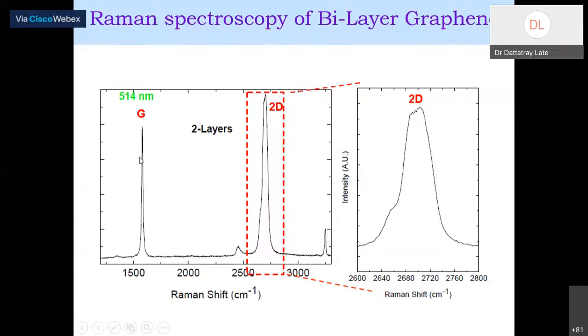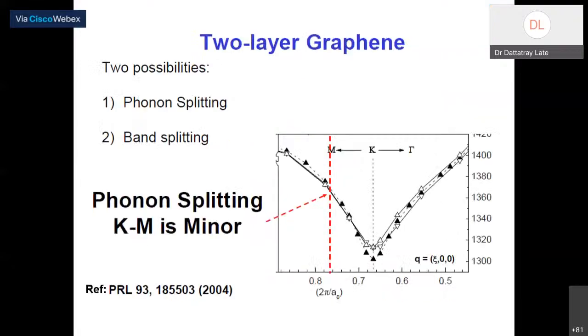You can see here also, the moment we have two-layer graphene, the intensity of the G band and 2D band is nearly similar, and the spectrum we fit in monolayer graphene is different here. You can see we are no longer able to fit this spectrum with a single Lorentzian or Gaussian. We need to fit it as multi-layer graphene because now we have two layers of graphene, right? The Raman spectra of one layer, two layers, and three layers of graphene are completely different. So by Raman spectroscopy alone, we can identify whether your graphene is monolayer, bilayer, three layer, four layer, multi-layer, or bulk graphite.